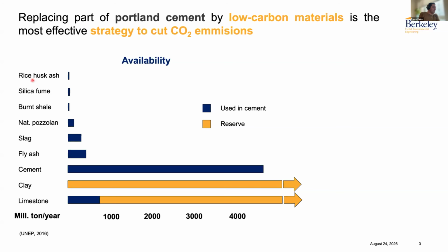But the problem is that many of these materials are not available in the quantities that we need them to replace, let's say, 50% of the clinker in our cement considering current demand. And why 50%? Because that's the estimation that the GCCA established for clinker factor to achieve carbon neutrality by 2050. And this is where these emerging, if you want, supplementary cementitious materials like calcined clays and limestone start to occupy a big role because they are highly available and they are in general cheap to obtain for cement producers.